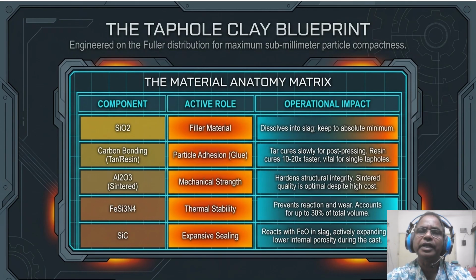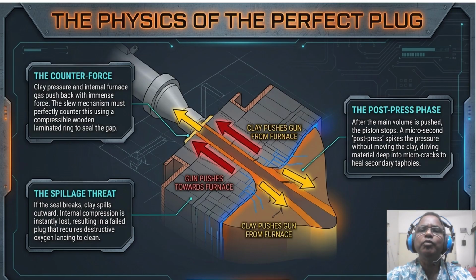So even the best clay chemistry is useless if the mechanical delivery doesn't create a perfect seal. Slide 7 illustrates the high-stakes moment of closing the hole. The clay gun must perfectly counter the immense internal furnace gas pressure. We use a compressible wooden laminated ring to seal the gap between the gun and the taphole face. So post press phase, let us discuss.